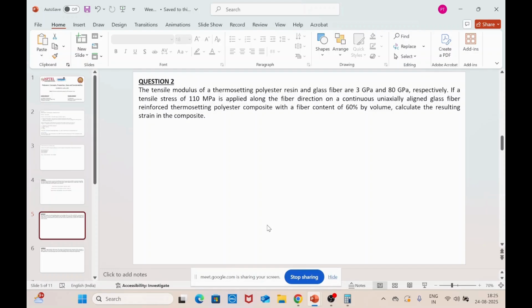You are given the percentage of the filler or the fiber content in the composite. You are also told that the composite is going to be subjected to a tensile stress of 110 megapascal, which is along the direction of the fiber. Now using this, you are supposed to calculate the resulting strain in the composite. So this is typically very similar to the previous problem. Here we just have an additional step to calculate the strain based on the stress that is acting on the composite.